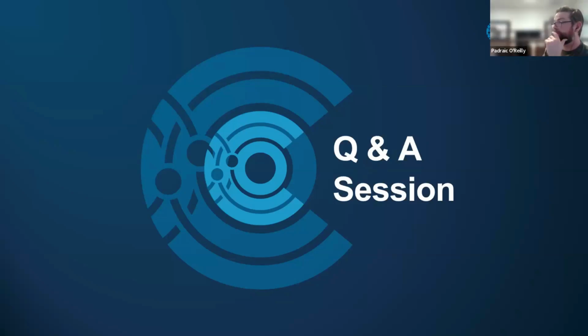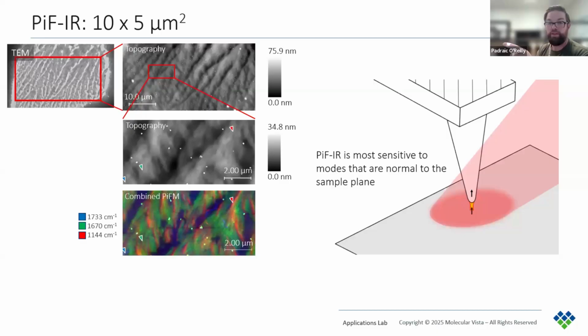Yeah, no, exactly. So basically, can I briefly show my screen if that's okay? Yes. Let me pull up one of the slides that was in my presentation that might show this a bit more clearly. Okay, so this kind of shows it a little bit here. I didn't really go into it that much, but basically at the tip apex, what we're seeing is we formed what we call a hotspot right at the tip apex. So where you have the laser focused at the tip sample junction, the tip sample interface, we effectively have a hotspot right at the tip apex. So that's actually what's measuring the PiFM.